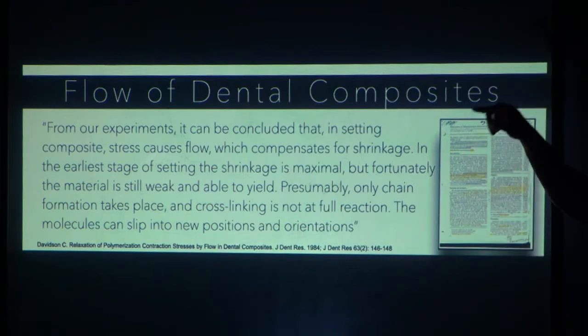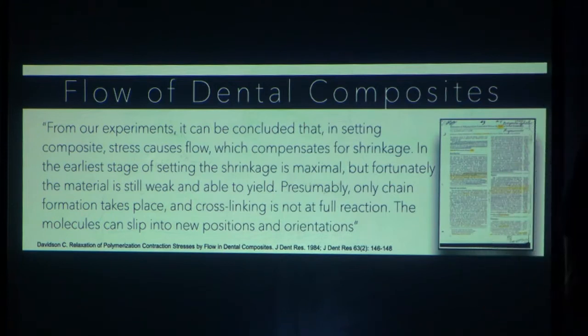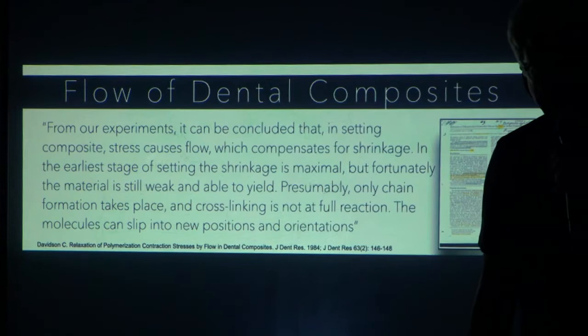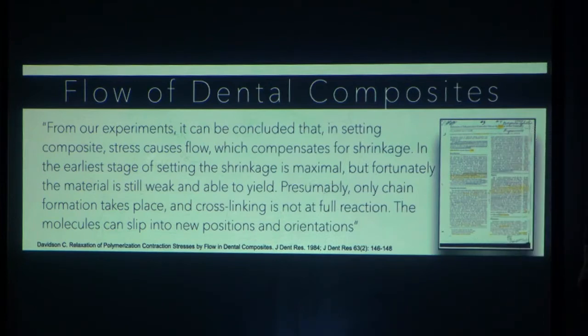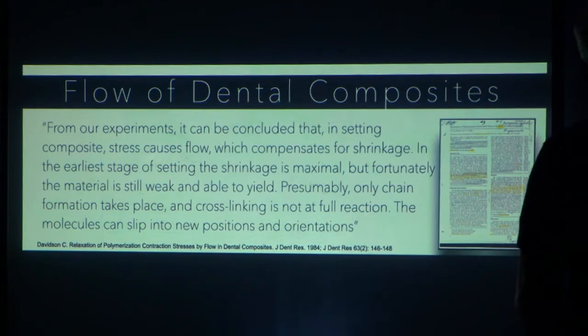This paper is fundamental, but there's a fundamental thing when you read this that your mentor needs to tell you, and that is they are only testing chemical cure composites. And the chemical cure composites are slow to polymerize because their photoinitiator is not there. There's no photoinitiation in true chemical cure composites. There's only a peroxide and an amine initiator that throws out about a fifth of the amount of free radicals. And so the polymerization would take 5 minutes instead of what it would take a minute in a photoactivated composite.